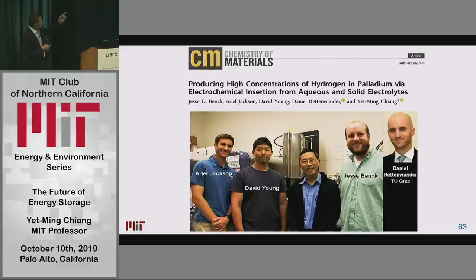It has to do with getting a very high concentration of hydrogen in palladium, so that there's the opportunity for cold fusion should it be favorable. The theoretical basis that would tell us exactly what we need to achieve in terms of hydrogen concentration and local structure is not yet known. But all the evidence from prior work suggests that you at least have to get to very high hydrogen concentration. And this is where the electrochemistry comes in.